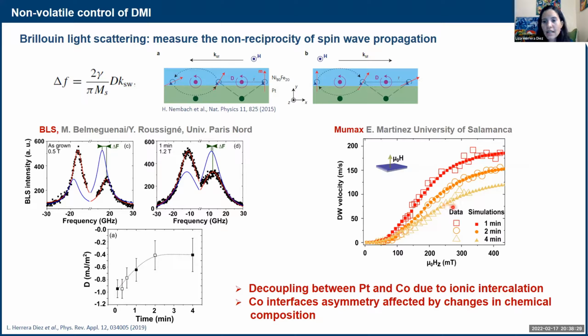We see actually the effects of this in the domain wall dynamics. We know that the domain wall dynamics at high fields depend also on D over ms. So this goes very well with the reduction of DMI. So the velocities decrease critically as you increase the time of the gate bias.